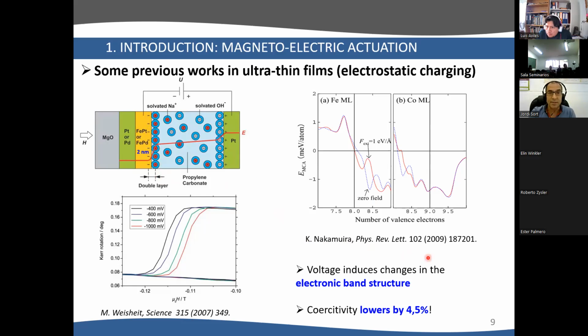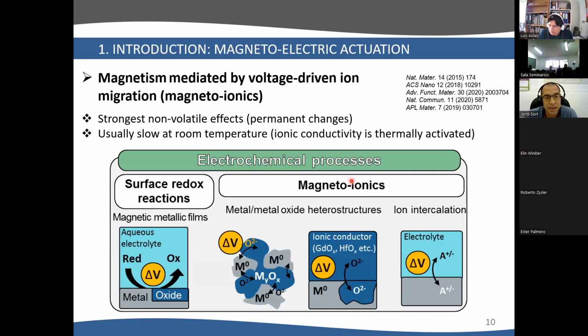But as I was saying, this is limited to ultra-thin metallic films, and to overcome this, people use another mechanism, which is magneto-ionics, and this is what I'm mainly focusing on in this presentation. What is magneto-ionics? It's the change of magnetic properties due to voltage-driven ion motion. The most simple case you could think of is a redox reaction where you have an iron film, you immerse it in an aqueous electrolyte, you apply voltage, and then this iron gets reduced or oxidized. Of course, this will change the magnetic properties of iron.